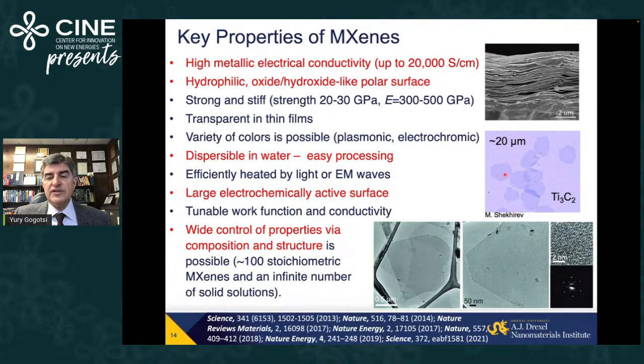You will never see flakes of that size of oxide or moly disulfide, for example. They will just break from vibrations when you process them here. MXenes survive because of extreme strengths. But moreover, unlike graphene, it comes not only in shades of gray, those are plasmonic materials with a variety of colors that you could see in the first slide that I showed to you here.